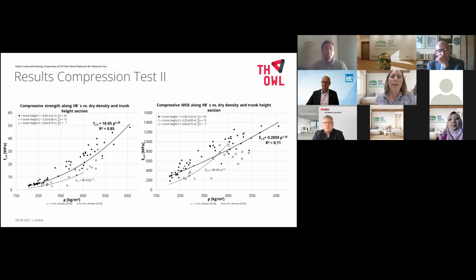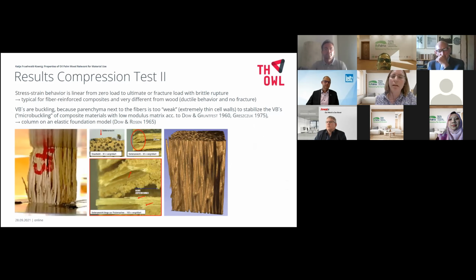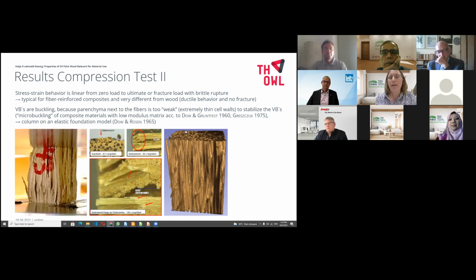The stress-strain behavior of the compression test parallel is linear from zero load to the ultimate or fracture load with brittle rupture. This is typical for fiber reinforcements and very different from common wood species with ductile behavior and no fracture. The vascular bundles are buckling. The buckling failure of the individual vascular bundles could be heard and is analyzed afterwards microscopically and in a 3D reconstruction. This is because the parenchyma next to the fibers is too weak to stabilize the bundles.